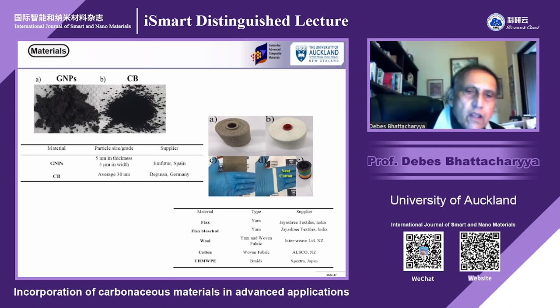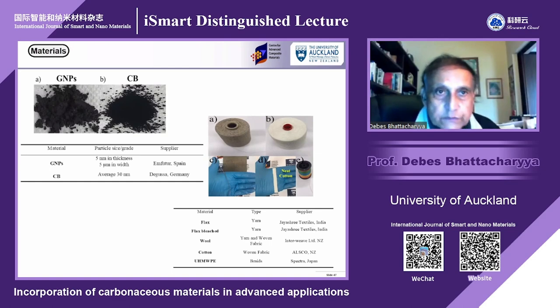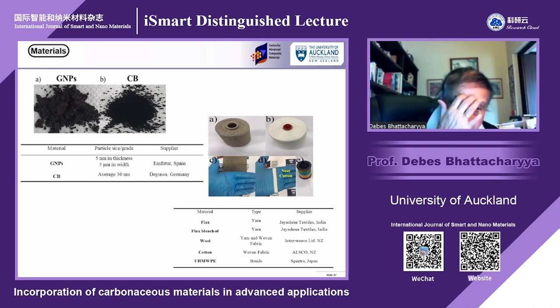So we have GNP and carbon black. Already we have shown that hybrid composites are better, so we did not want to waste any more time. We actually started with graphene nanoplatelets plus carbon black, and started with flax. I'll show you various materials: flax yarn, flax bleached yarn, you can see it is white, then wool, then cotton, and then an ultra high molecular weight polyethylene material as well. For braids, we used that Spectra, which is available in the market. So we used all sorts of natural materials and one synthetic material. I'll show you results only for the natural materials.